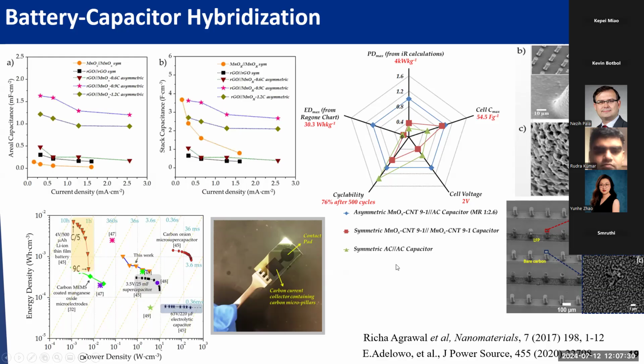We also have a different setup, like a manganese oxide-based capacitor material. We have a symmetric capacitor too. For example, Richa worked on active carbon paired with manganese oxide and CNT composite. We try to understand how to optimize and match the two materials, which have very different properties, because for the battery materials, we have a high energy, but at the same time, the charge storage is either an intercalation or conversion mechanism, or some materials have an alloying mechanism.